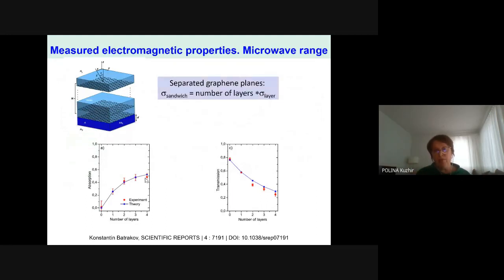So now I come to the original results collected in our teams, both in the Minsk Nanoelectromagnetic Lab and at the University of Eastern Finland, who provided us with particular experimental samples. We found that with graphene of not perfect quality, like our CVD graphene, we need not 2 but 4 graphene layers stacked into a sandwich structure to achieve this golden 50% absorption of electromagnetic radiation.